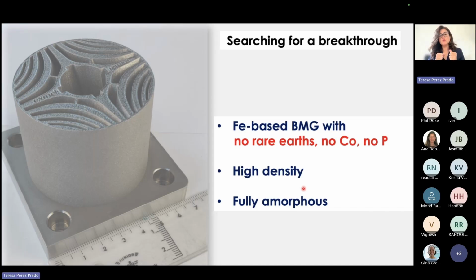I would say more difficult, because we were not satisfied with just printing any iron-based bulk metallic glass. We wanted a composition that had no rare earths because of all the supply problems, no cobalt because of the social impact, and no phosphorus because phosphorus is very volatile and then you cannot control the composition and so on. So we wanted to get one of these alloys, and these alloys are extra complex because they have a very, very small glass formability. Glass formability means that even if I take this certain composition in the liquid state, I cool it down very, very fast at the right cooling rates, still I can only produce a certain thickness of material in amorphous form, and for these materials, this thickness is about 100, 120 microns.